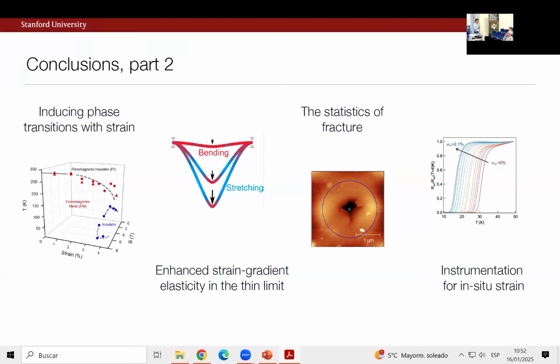Yeah, on my computer, at least, we have a little bit more now experimental probes of that lattice constant variation. So another version of these sorts of things we're utilizing is to do in situ strain under X-ray scattering, like in synchrotron environments. Believe me right now, and I can show you later that I think that looks pretty good. But certainly this is a function of the geometry. So it's not generically impossible. What you say absolutely does happen. It just turns out to be a minor contribution for the geometries we're using.